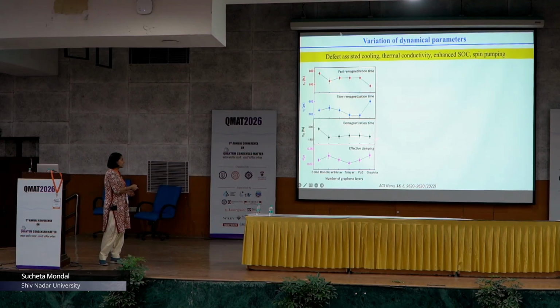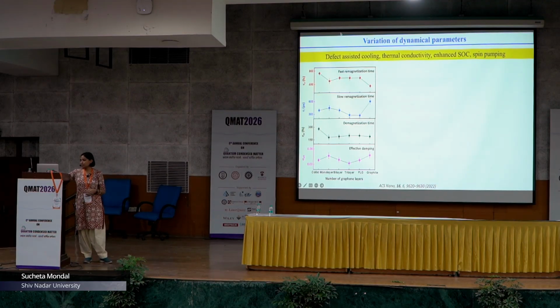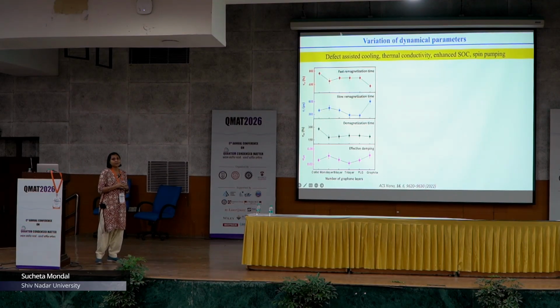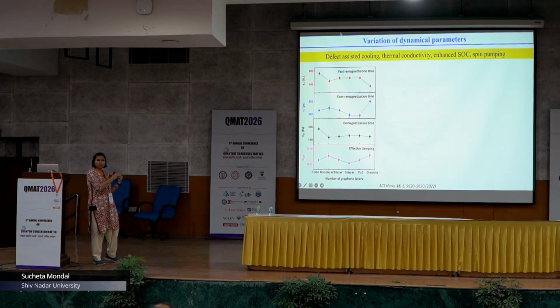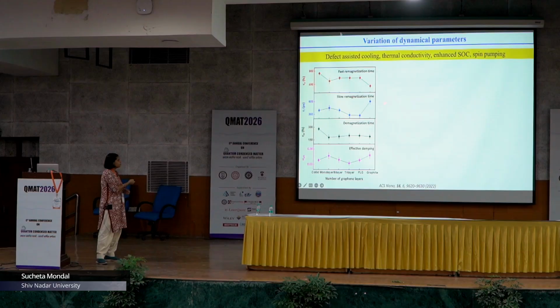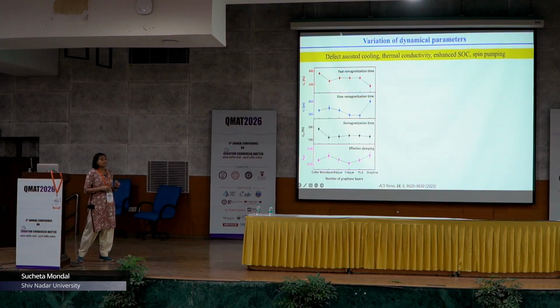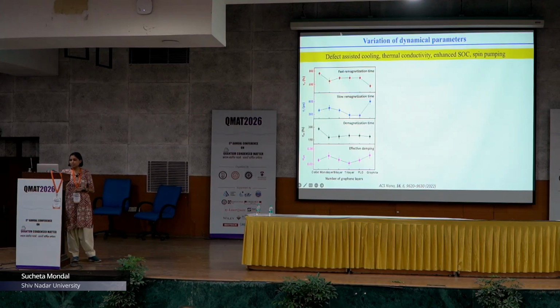Similarly, for demagnetization time also, the enhancement of SOC might be introducing spin flip scattering in the system, and that is why demagnetization time and damping had an inverse relationship for most of the samples. Slow demagnetization time is getting affected non-monotonically, and for graphite it is very high, because graphite is not allowing the deposited heat to pass easily from the probed region to the substrate, to the lattice. So, it is restricting, and that is why the lifetime is increasing. The fast demagnetization time is decreasing because there is not only electron-electron scattering, but also phonon mediated or acoustic phonon mediated scattering, which is causing such changes in the sample.